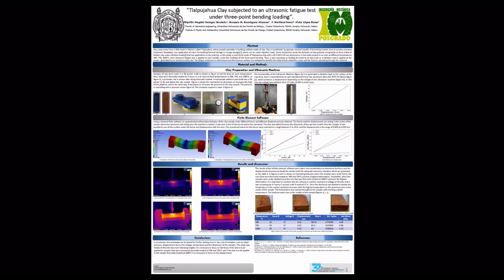Using finite element software, we obtained an approximation of the deformation behavior of the clay sample under different forces and different displacements. The forces and the displacement act at the center of the sample, where the aluminum horn acted once the machine started. It was over a slice of aluminum where the horn acted. The slice was added because the dimension of the horn was smaller than the sample. With the slice, it was possible to use all the surface under the forces and displacement.